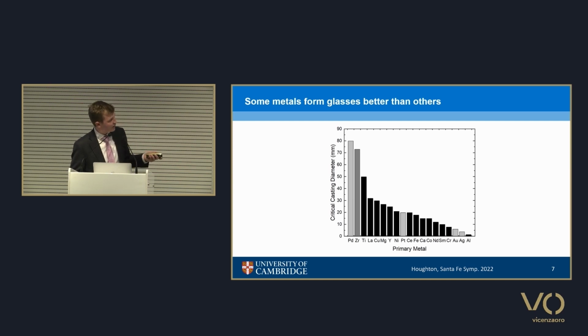So here we've got all various types of metallic glasses. As you can see, palladium's nice and high at the top, and gold is more towards the bottom. It's worth noting that there are very few silver glass forming alloys, and none of them are near the sterling silver fineness regulations. We've got our palladium glasses up here, and then we've also got these zirconium ones. For some of you familiar with the watch trade, these zirconium-based metallic glasses have already been used under the trade name liquid metal and are often used in bezels of certain watches.